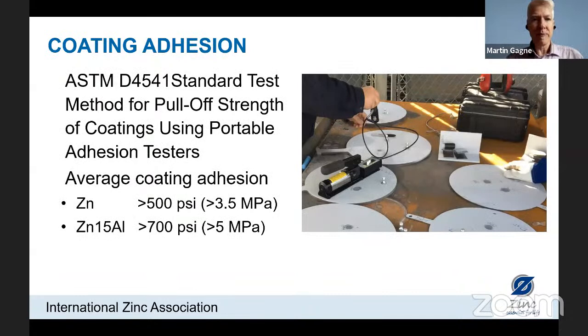Along with testing the surface roughness, we also want to measure the coating adhesion after the zinc has been applied. Another ASTM test, D4541, standard pull-off test. So now with pure zinc coatings, we generally achieve higher than 3.5 megapascals, and the zinc 15% aluminum has slightly higher. We achieve better than 5 megapascals of pull-off strength. Again, these are significantly higher than most paint bond strengths.